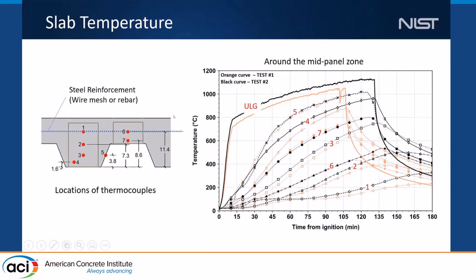And this is the slab temperature, especially away from the steel beam underneath. So basically the bottom side of the concrete slab or the steel decking is directly exposed to fire. And here it shows the test number 1 results with the orange curves, and the black curves indicate the test number 2 results of the temperatures at different locations. As you can see, given the fire condition was pretty similar, the temperature evolution within the concrete was also pretty similar.